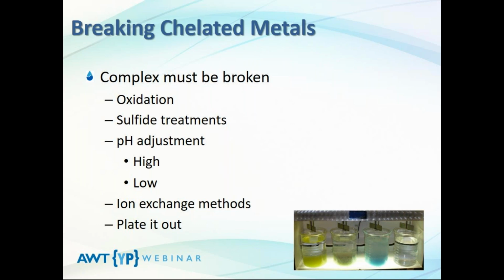Zinc nickel alloy has a very unique chelant in it. Think about what I'm saying when I'm saying zinc nickel alloy. I am hydrotroping, for lack of a better term, two metals together to form one soluble complex for electrodeposition onto the substrate. I've got to keep zinc in solution. I've got to keep nickel in solution in order to maximize my deposition. And my chelant of choice in this case, in many cases, is an amine. Is a triethanolamine, a monoethanolamine, a diethanolamine, or a combination of the above.